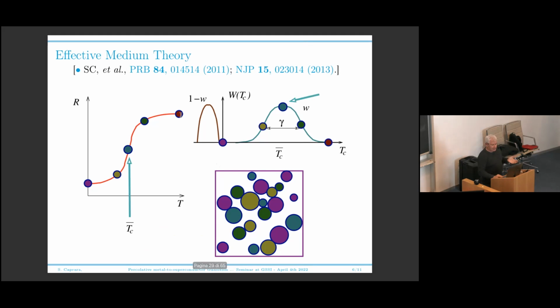So this description is satisfactory. And from the point of view of the data, don't forget that you measure a resistance curve. So this curve is measured. If you assume that your distribution is a Gaussian, or say symmetric, then the inflection point of this resistance curve is a direct measurement of the average critical temperature in your sample. And the width of the transition is a direct measure of the width of the distribution of critical temperatures in your samples. So you can extract directly from the experiments some information about the distribution of your critical temperature.